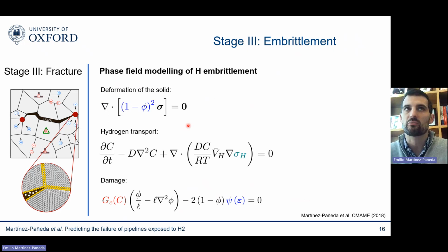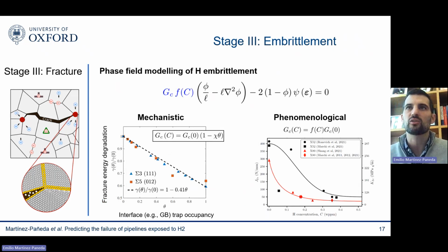So it's an equation for the deformation of the solid, one for the hydrogen transport that I will discuss, and then one for the evolution of the damage in the phase field equation. I'm highlighting here some of the couplings, but the key coupling, of course, is how hydrogen interacts with the toughness of the material. We know qualitatively what happens. Hydrogen reduces the fracture energy, but how to define this quantitatively is the key question.